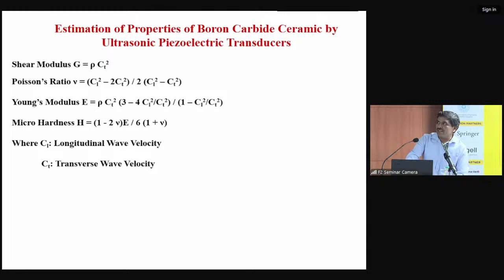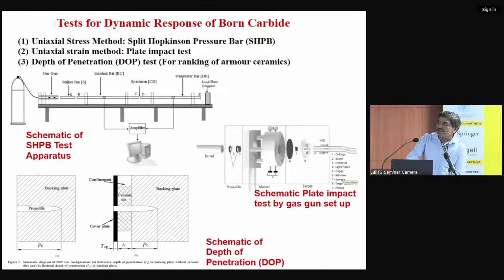So here the estimation of the properties is also very important. These are a few formulae where we can estimate, and one of the important properties is the dynamic compressive strength. We are estimating it at IIT Kanpur because Professor Venkitanarayanan sir is there. He is the core expert and he is also my guide. High strain rate property means the dynamic compressive strength, using the split Hopkinson pressure bar, because ceramic is not easy to handle, and doing this test for different grades of ceramic requires a lot of expertise for the preparation of the specimen, and also to do the testing, because a lot of samples go to waste. So this is a special technique, and we are using the facility of IIT Kanpur.